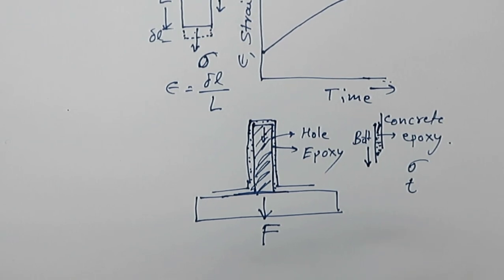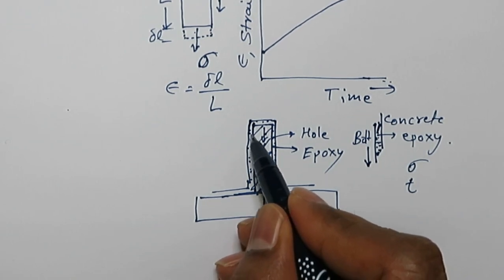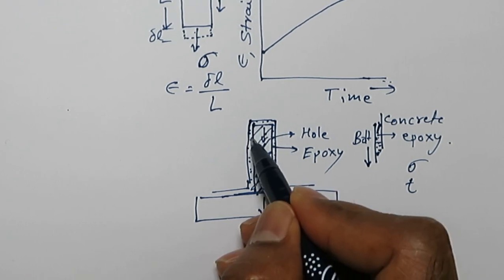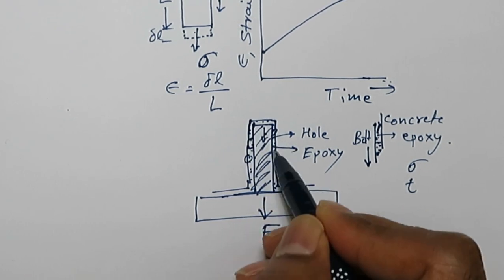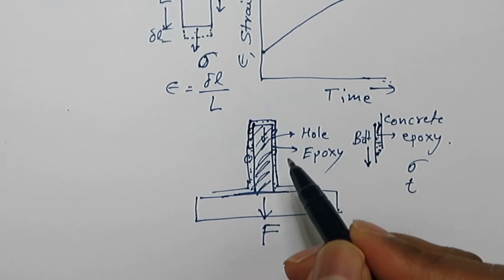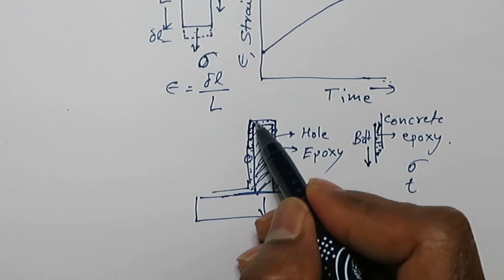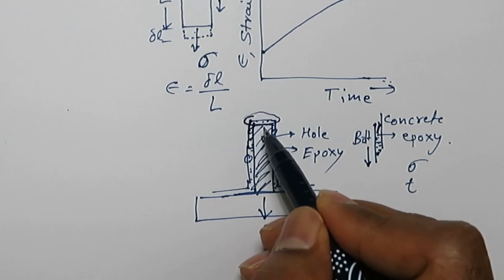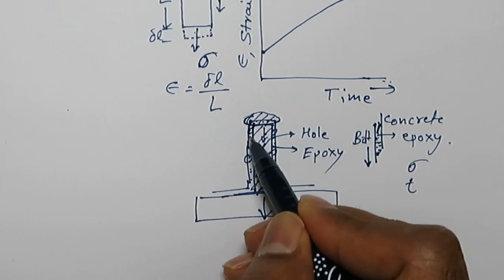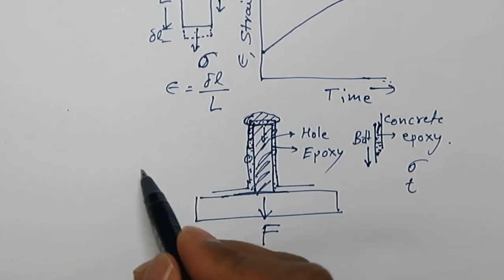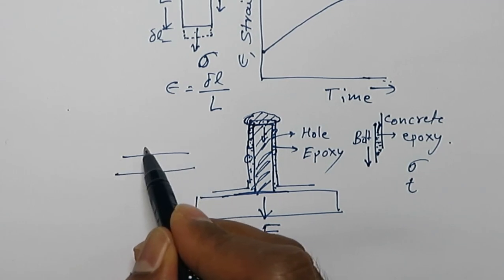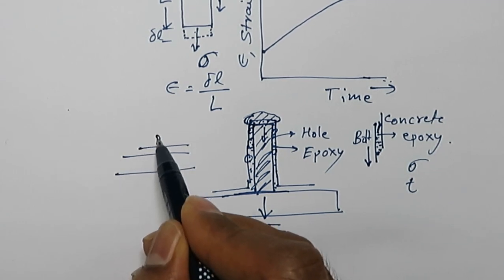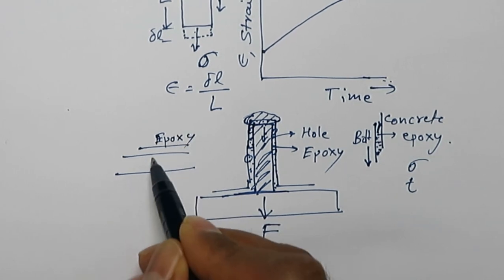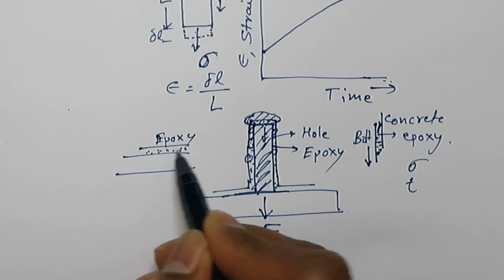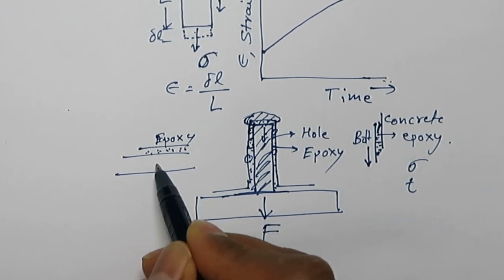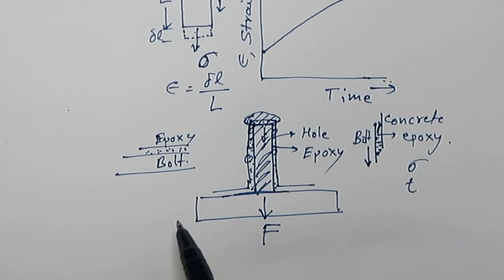There were some other mistakes. For example, the epoxy was not applied sufficiently, so there were many dry areas. That means areas which had no epoxy. That's one mistake that was done. Another was that there were a lot of dust particles inside the hole. So for example, some residue was there, a lot of dust particles. So because of the dust particles, the bonding between the bolt and epoxy was not complete. So there were a lot of dust particles in between. Because of the dust particles, the bonding between epoxy and the bolt did not take place properly.